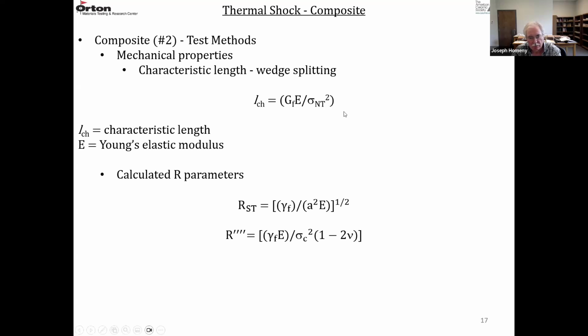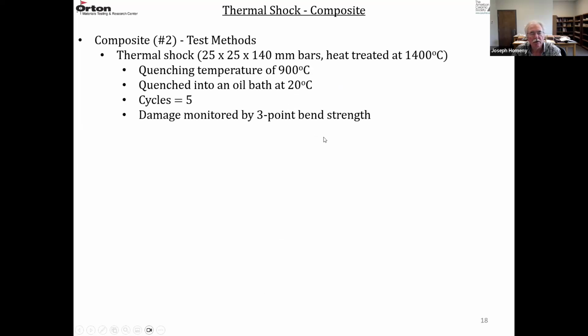I'm not sure why they... well, I guess this is not a triaxial stress state. That's why this 1 minus 2 nu term is not needed. So LCH is very similar to R4 prime. The thermal shock was done on 25 by 25 by 140 millimeter bars. These bars were coked at 1400 degrees C before thermal shocking. So that pyrolyzes the resin. The quenching temperature was 900. They were dropped into an oil bath, which was held at 20 degrees C. Each bar had 5 cycles, and then they measured the bend strength before and after cycling.